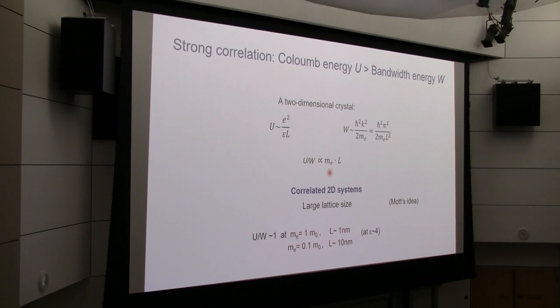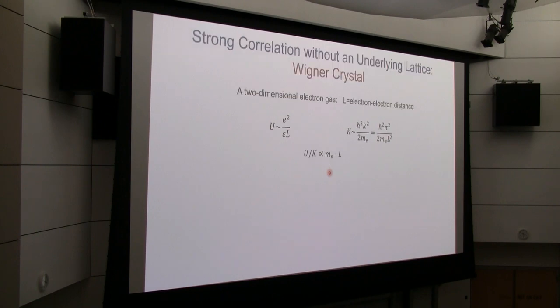And this argument is very general and has been discovered at different times in different systems. And another very important example of using the same argument is a strong correlation of 2D electron gas when there is no underlying lattice at all. So Wigner basically says, if you don't have underlying lattice, there is still a characteristic length scale, and that is electron-electron separation determined by the density. And he basically used exactly the same argument.